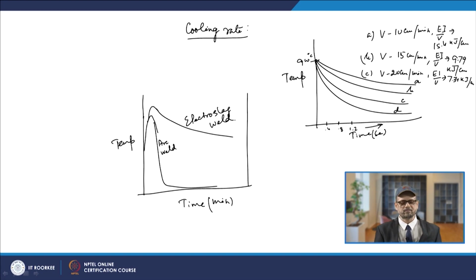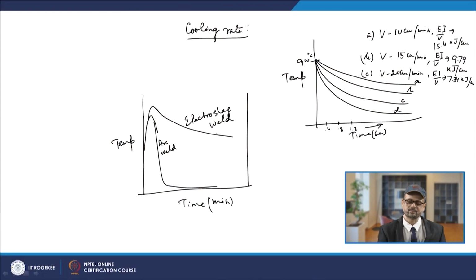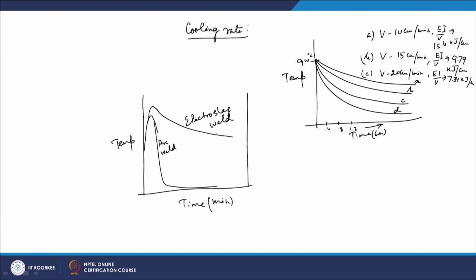Now if you see in this arc weld, your temperature is coming down very quickly, and here the temperature goes somewhat higher and then comes down very slowly in this fashion. So the cooling rate in the case of arc weld is quite high, because the slope is quite high as compared to electroslag welding. As you also understand, in the case of electroslag welding the heat input, Q by V value, is very high, and because the Q by V value is very high, your cooling rate is very small in the case of electroslag welding.